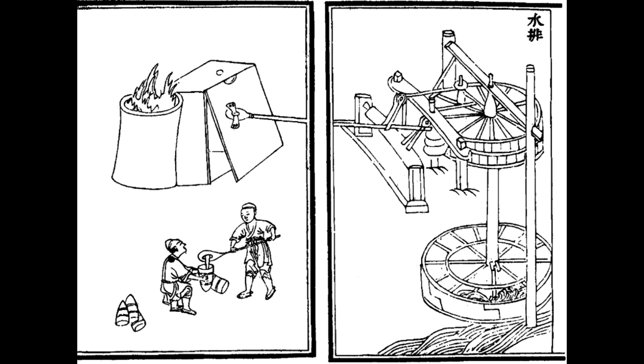Now, it is important to note which parts of the production process cast iron production replaces and which it doesn't. For very low-grade iron products, things that can actually be directly cast, cast iron production might actually replace both the smelting, that is, the bloomery, and some of the forging work of producing an iron object. But for most iron objects, including nearly all tools and weapons, cast iron production essentially replaces only the smelting process, while malleabilization would replace the carburization process with a decarburization process.